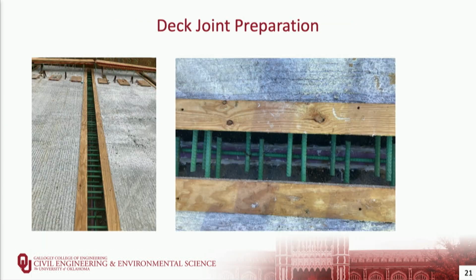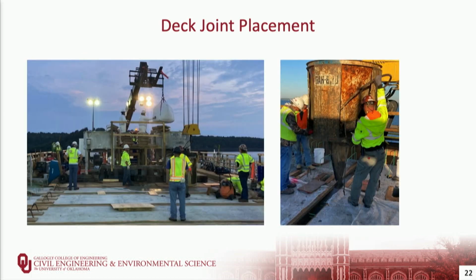So once they got onto the actual bridge itself, they placed these span by span. I think by the end of the project, they were doing 2 spans at a time. But the joints were prepared with these wood strips along the side to cast the joints high so they could come back and grind after the fact. And then on the back of that picture on the left, you can see the shear pockets that are covered up with pieces of plywood. The joints were placed mostly at night because it was very hot when they started in August.